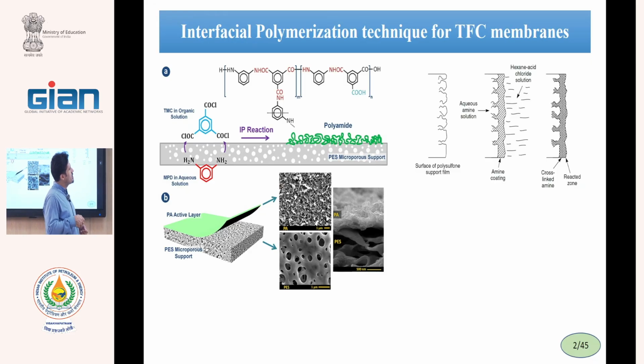One step is preparation of the support. We need a good support for coating of this layer, and the porosity and the material of this porous support are important. Mostly, we use a polysulfone ultrafiltration membrane for fabrication of NF and RO membranes. But this support can be ceramic, or another polymer, polyethersulfone, PVDF, PTFE, and all of these polymers and materials can be used. But in RO membranes, most use polysulfone because it has good chemical resistance, good compaction resistance, and the price is relatively low.